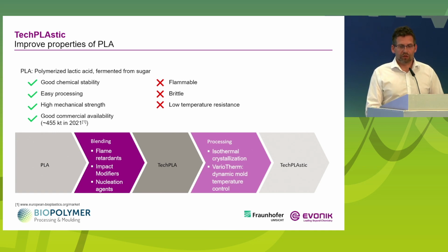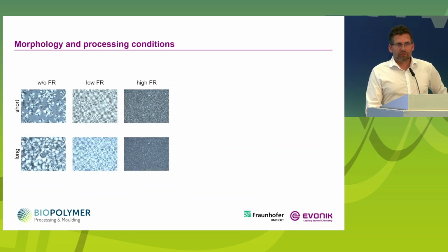property. And we did not add only these ingredients, but we had also looked to the processing, and there we looked at both an isothermal crystallization and also a variothermal injection molding process. Yeah, when we talk about impact strength or flame resistance, it's easy to add a certain additive, but when we talk about the heat resistance, it's more depending on the morphology of the compound. And if we have a look on the left side, we see on the upper side a short cooling time, and on the lower a longer cooling time, that we increase the crystallization with longer times.